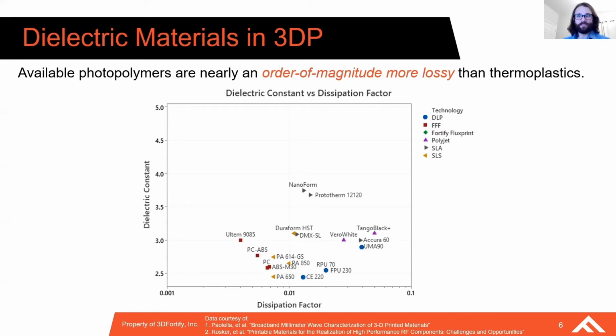When thinking about this critical performance characteristic, the dissipation factor, photopolymers have always struggled to compete. Looking at this chart plotting the dielectric constant on the y-axis of a variety of 3D printable materials to their dissipation or loss factor on the x-axis, which is in a logarithmic scale, we can basically draw a line right down the center. To the right, where the materials have higher loss, you'll mostly find photopolymers. On the left, in the direction of the lower loss, you'll mostly find thermoplastics. These thermoplastic materials inherently exhibit lower loss characteristics.